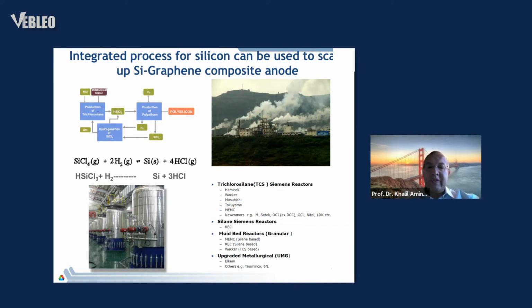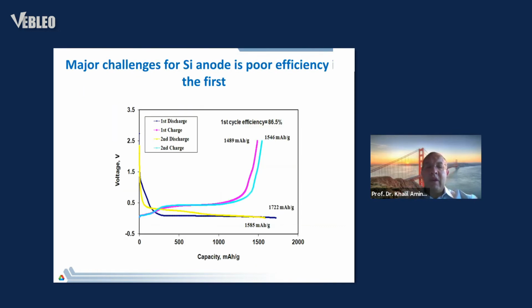So the cost will be very significantly lower. Now, again, the biggest problem with the silicon is the large irreversible loss. Notice here, for example, the difference between the charge and discharge is almost 150 or 180 milliamp hour per gram. That's basically the capacity of the cathode.